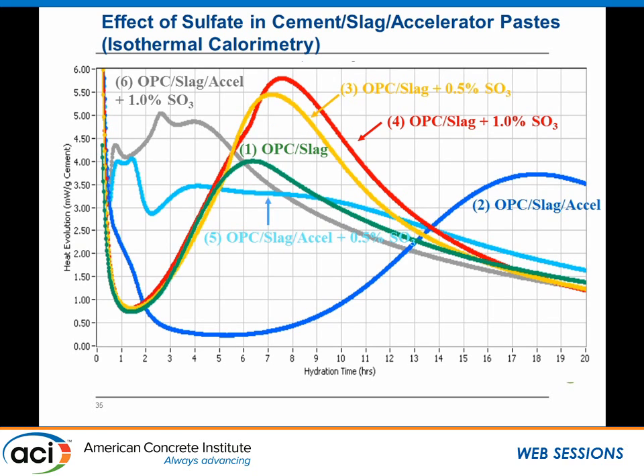So in here, really, just one last example we are looking at is the ordinary Portland cement with 40% slag. When we add the accelerator, we saw actually the reverse effect, right? We are getting a retardation. When the OPC with slag is added in with a different sulfate level, we do see an increase in the hydration. And now when we added the accelerator with this mix with a different sulfate level, at the correct sulfate level, we actually do see a really good acceleration effect. So until we do this, I think it's very difficult, at least for me, to predict what can be happening.